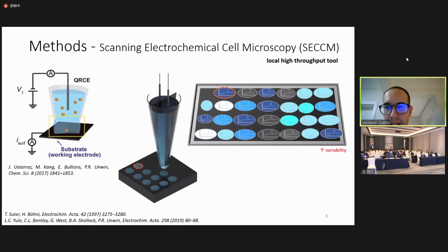For the first three aims we are chasing, the first three studies, we employed a local electrochemical tool, and it acts in a high throughput mode. In fact, it's a miniaturized version of a classic three-electrode electrochemical cell. And we can probe the surface, and at each location, we can run individual potentiostat-based tests. For the first two studies we will be discussing, we have done potentiodynamic polarization, and for the third one, we have done potentiostatic.